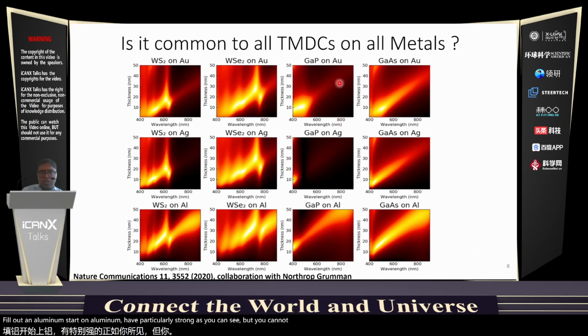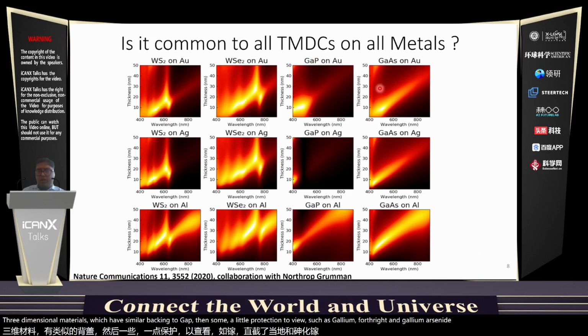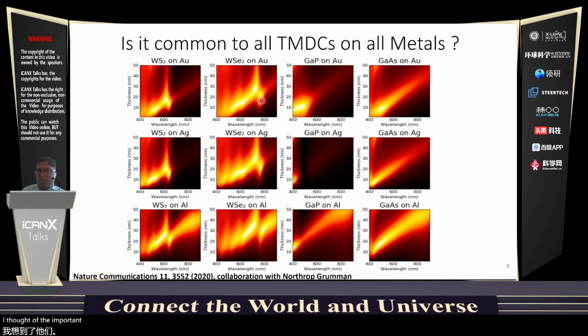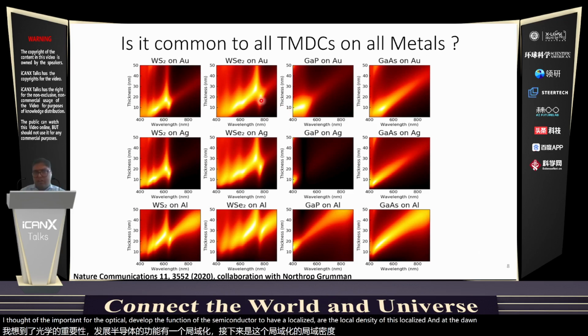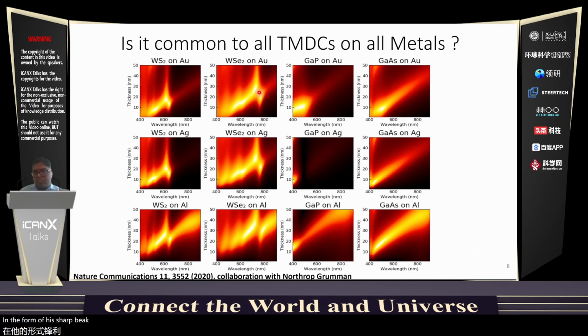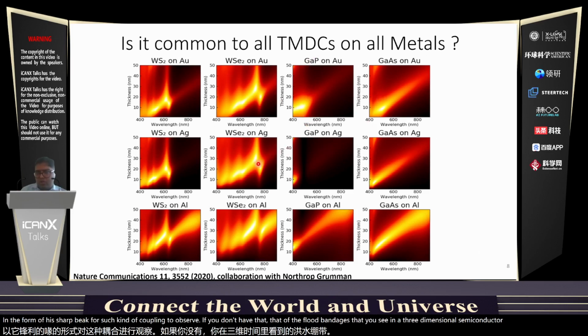But you cannot see the same thing in three-dimensional materials, which have similar band gaps and similar refractive indices, such as gallium phosphide and gallium arsenide. And so it is important for the optical dielectric function of the semiconductor to have the local density of states localized in excitons, in the form of these sharp peaks, for such coupling to be observed. If you don't have that, such as the flat band edges that you see in three-dimensional semiconductors, you are not going to see this strong-coupling-like behavior.